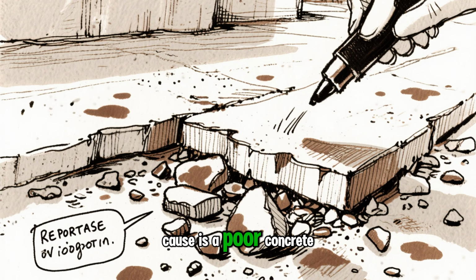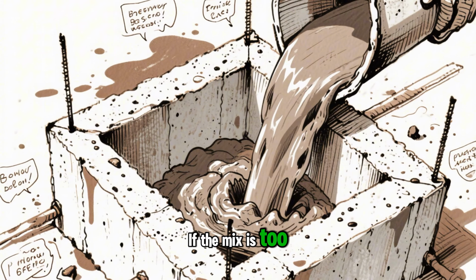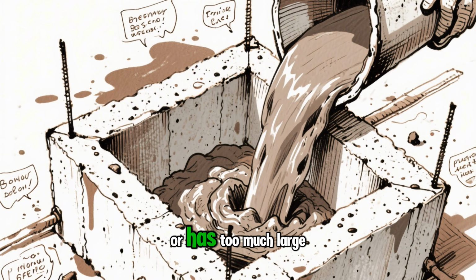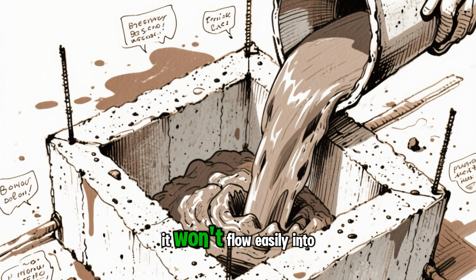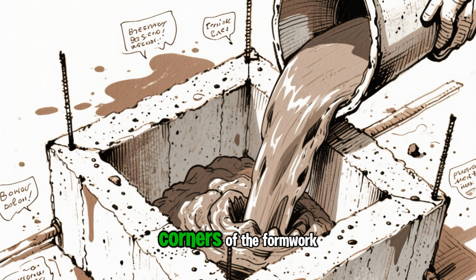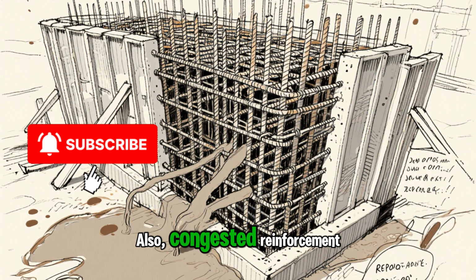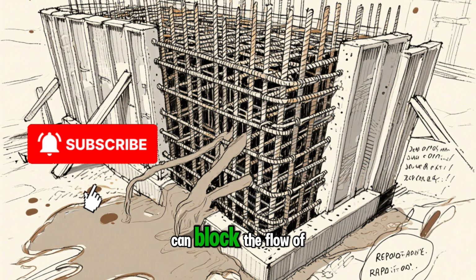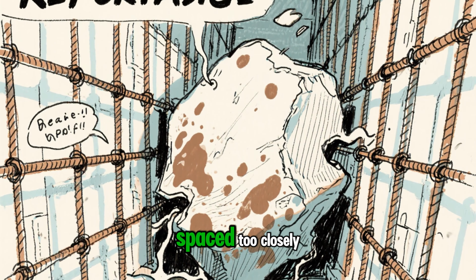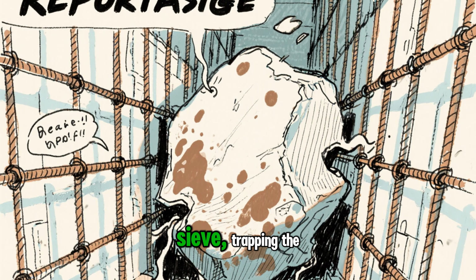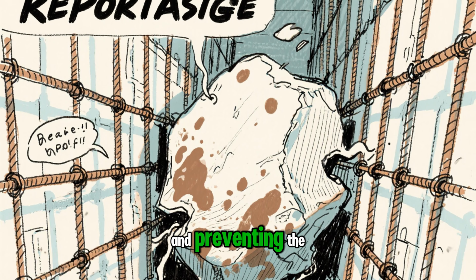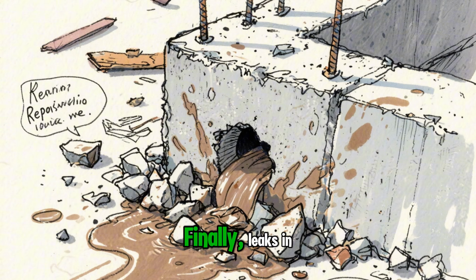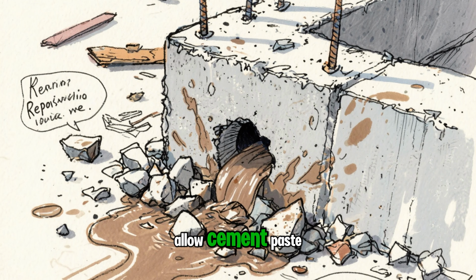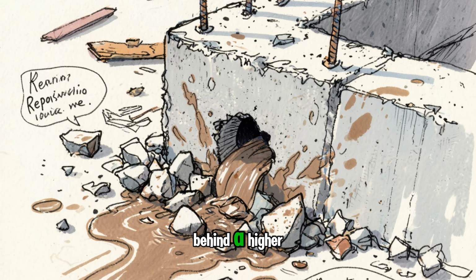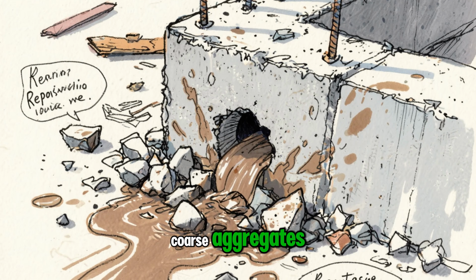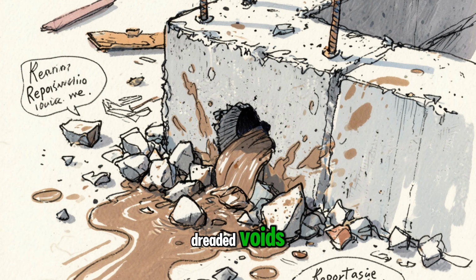Another common cause is a poor concrete mix design. If the mix is too stiff, too dry, or has too much large aggregate, it won't flow easily into all the corners of the formwork. Also, congested reinforcement can block the flow of concrete. When rebar is spaced too closely, it acts like a sieve, trapping the large aggregates and preventing the mortar from passing through. Finally, leaks in the formwork can allow cement paste to escape, leaving behind a higher concentration of coarse aggregates and creating those dreaded voids.